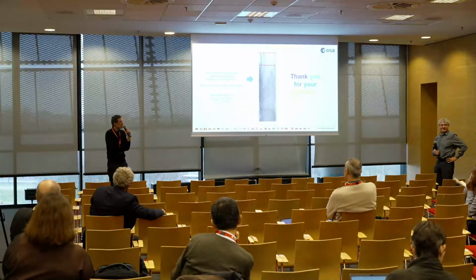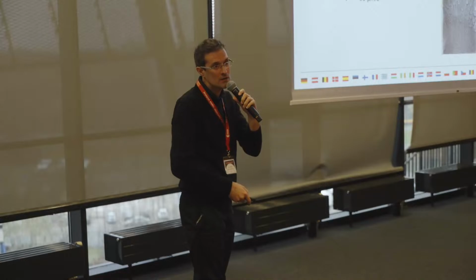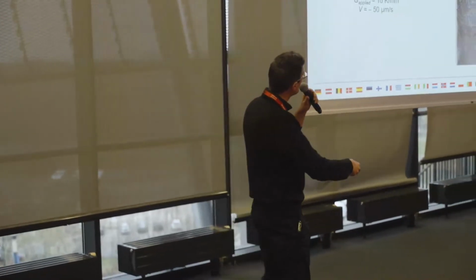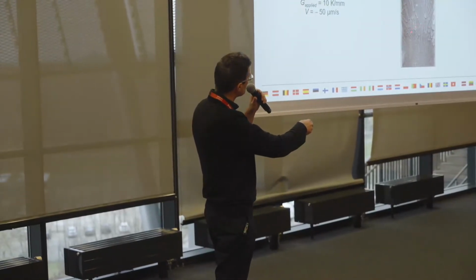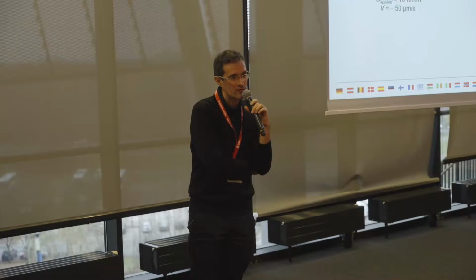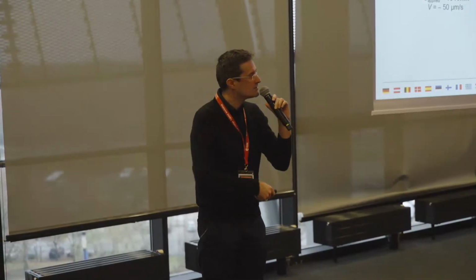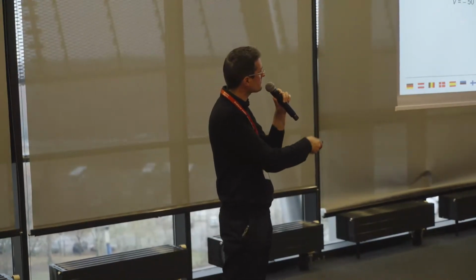Sure. Size distribution, and yes, these are the same characterization as the one shown by Sonia in a previous talk. There are typical morphological features for these crystal grains. When we measure the primary spacing, which would be the distance between each grain, the secondary arm spacing, as you can see, maybe here there are secondary arms, so there are many models to characterize and compare these typical features that will have an impact on the mechanical properties, of course, of the metal alloy. So this has been done for many years on micrographs in the lab, on static images, and it can be transposed to in situ observations, of course.